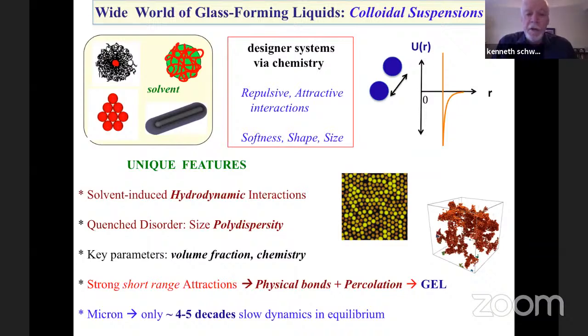Now, there's a number of notable and unique features of colloidal suspensions because they're mixtures. There's solvent-induced hydrodynamic interactions. There's quench disorder associated with size polydispersity. The key parameter is usually not temperature, rather it's volume fraction and controlling the chemistry, hence the interactions. And the presence of strong short-range attractions leads to the unique ability to form long-lived physical bonds, which in concert with percolation can lead to a different form of effectively arrested matter that we call a gel. One practical thing is if a traditional colloid is a micron in size, this means that you can only access of the order of 4 or 5 orders of magnitude of slow dynamics in equilibrium before you fall out of equilibrium.